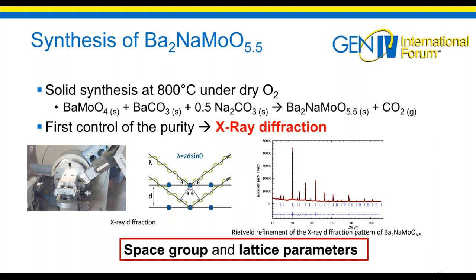When you do a synthesis like this, the first way to control the purity of your sample is the X-ray diffraction method. We obtain crystalline materials, and these types of materials are made of repeating planes that you can see here in all directions. They can be described with what we call a space group and cell parameters. When X-rays hit the sample, depending on the incident angle, they will be scattered or not. By collecting the scattered X-rays, you get a pattern that is really a fingerprint of the material. On this pattern, you can perform what we call the Rietveld refinement, and this will give you the space group and lattice parameters of your sample.